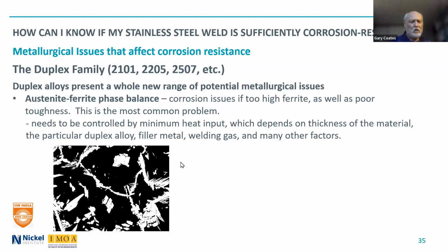And so this is a microstructure where the black is ferrite. You can see this has very high ferrite content. We really want it to be 50-50 or close to that, maybe 65 max.